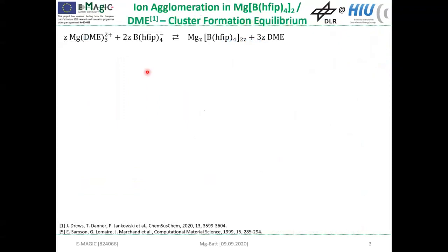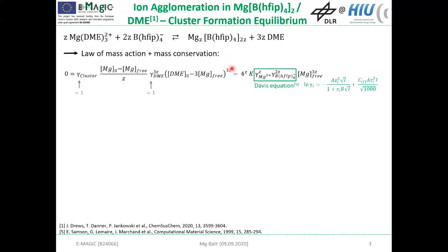As a first step, we had a closer look at the equilibrium between the dissociated ions and neutral clusters. During the ion agglomeration, solvent molecules are released from the solvation shell of the magnesium cation. And this leads to an increase in entropy, which is assumed to be the main driving force for these cluster formations. So when we now have a look at the law of mass action and the mass conservation, we get this formula which relates the amount of free magnesium to the electrolyte concentration.